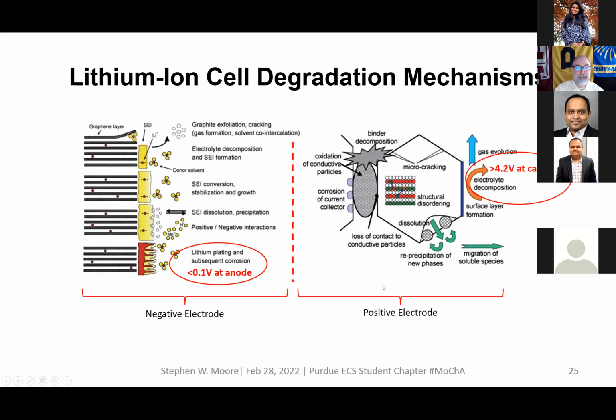I'm going to show you a diagram like this. So this is a diagram of some lithium-ion degradation mechanisms. And over here is the anode, which is the negative electrode. And on the right-hand side, I have the cathode, which is the positive electrode. And there's all sorts of things that can go wrong in a lithium-ion battery. And I could easily give you many hours of lecture over each one of these little topics. But some of the things are pretty easy to spot. Lithium plating: when you get around 0.1 volts at the anode, you can have some bad things happen with lithium. On the positive electrode, I have circled right here, you can get some bad things happening at your cathode, some electrolyte decomposition and some other things.